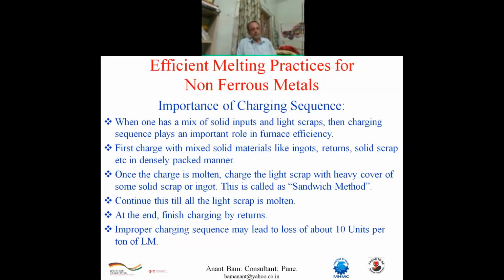Once the charge is molten, charge the light scrap first into the molten metal, top it up with some solid or heavy scrap on the top of it or some ingot on the top of it. This is called the sandwich method. From the bottom side, there is a liquid pool in which once the turning boring or light scrap enters, that liquid takes a viscous or semi-solid condition. Then further turning boring or light scrap is charged on it and it is densely packed further by putting some counterweight or some heavy material on the top of it. Thereby, once the light scrap is densely packed, electric conduction between all particles happens very fast and the melting process becomes easy.